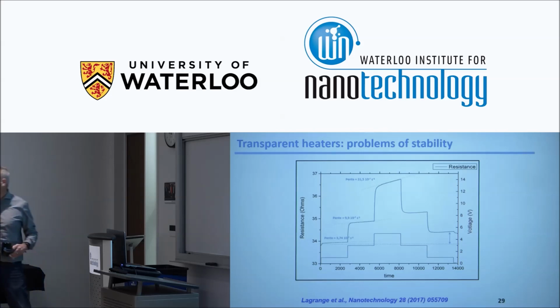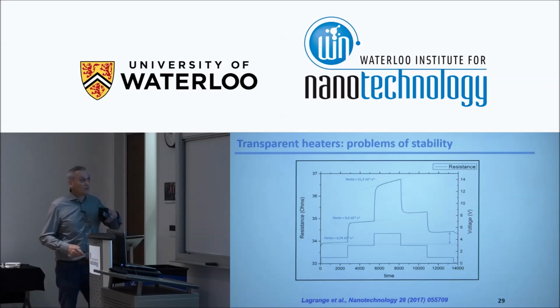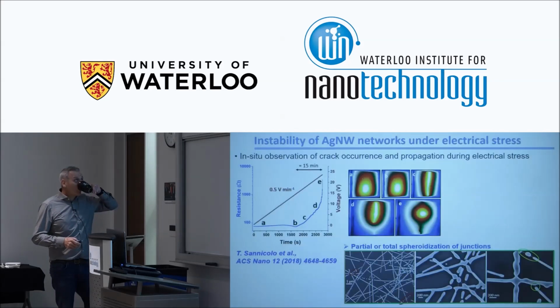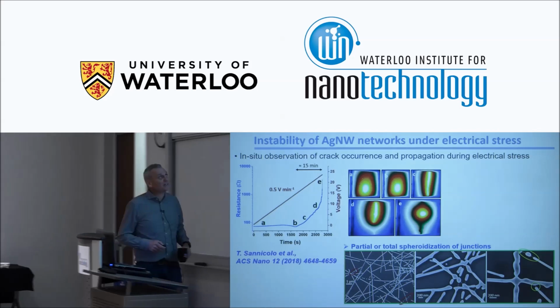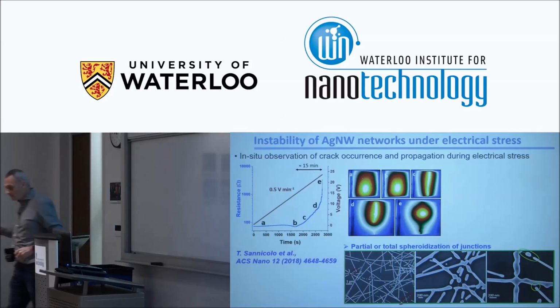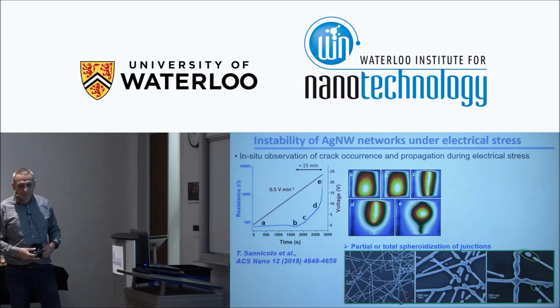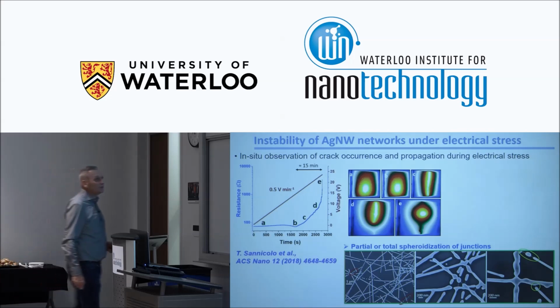It's not stable. And so if it's not stable, we are not able to integrate this transparent electrode in any device. So we have to work on that. And we wanted to understand where this instability is coming from. And from time to time, when we make, for example, a voltage ramp, we increase the voltage versus time linearly with a rate of 0.5 volt per minute. And we measure in situ the resistance. And first, the resistance is slightly increasing because of the Joule effect. And then there's a decrease of the resistance. This is electrical sintering. And then the resistance is increasing, and then it's diverging. And we wanted to understand that.